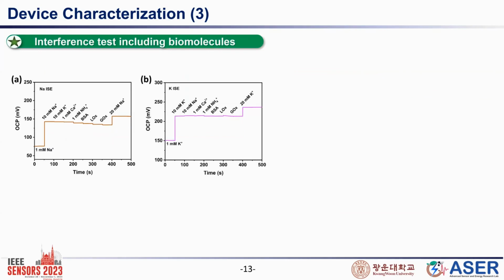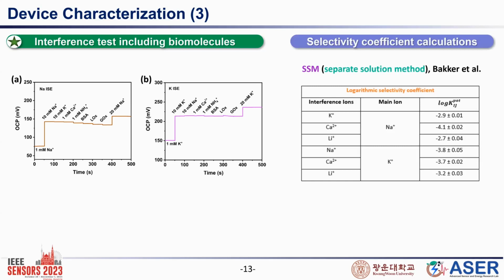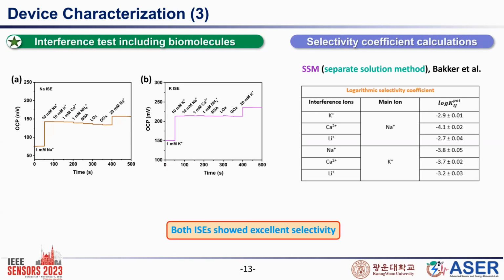And last of all, we have gone through the interference test. In this test, we have included some kinds of biomolecules along with our target electrolytes and others. So the result shows a very good, selective response for our ion selective electrode. There is no significant response to other interfering ions or biomolecules. And we have also calculated our logarithmic selectivity coefficient according to the Bakker scale, and we have got a very good selective nature of our electrode, and we have tabulated all the values. So I can say both the ISEs show excellent selectivity.